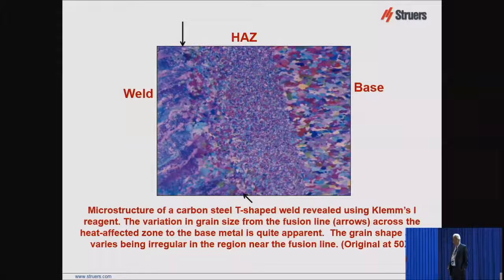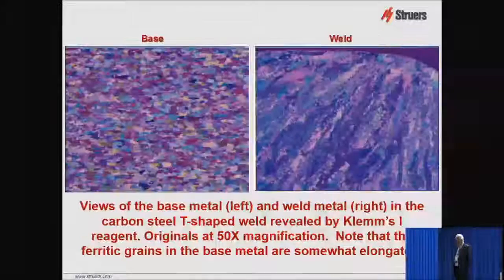And it really works well. If you have more martensite in a weld, higher carbon steels, higher alloy steels, I wouldn't probably use Klemm's. I'd probably use a different etchant, like 10% sodium metabisulfite, perhaps, or one of Beraha's sulfamic acid reagents. There's several you can choose.